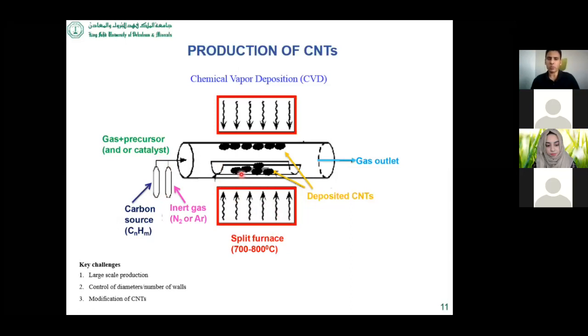Of course, there are various parameters that control this process: the choice of precursor material, the flow rate, the choice of the catalyst, and the temperature. I will not go into detail on those. Some key challenges here are that although CVD can be used for the production of a large amount of CNT, the production yield is still very low. Similarly, it's very hard to control the properties of the carbon nanotubes produced by this technique.